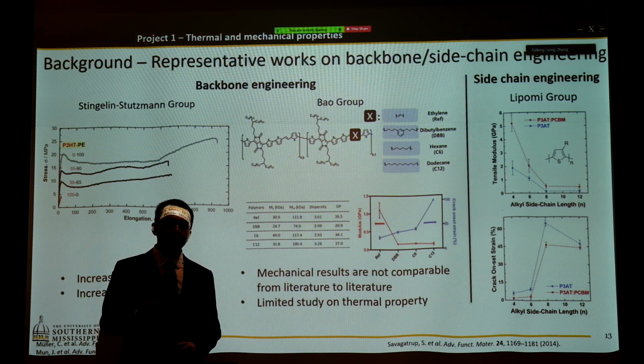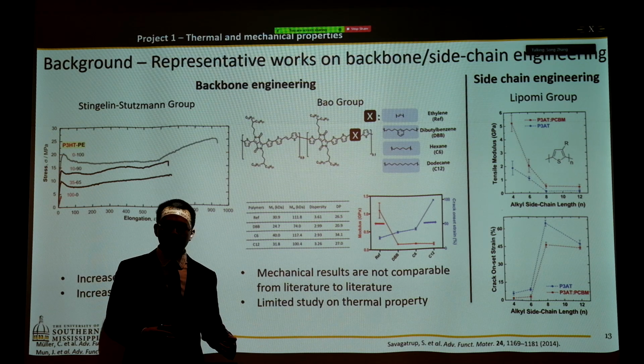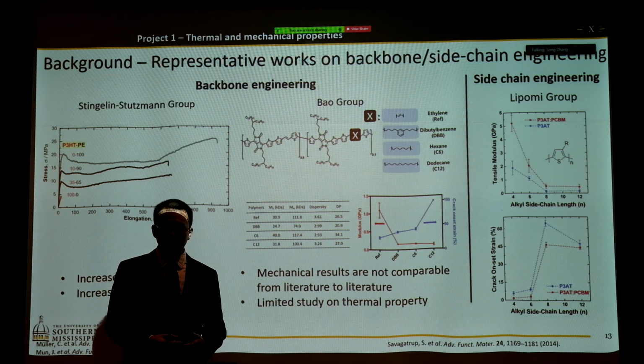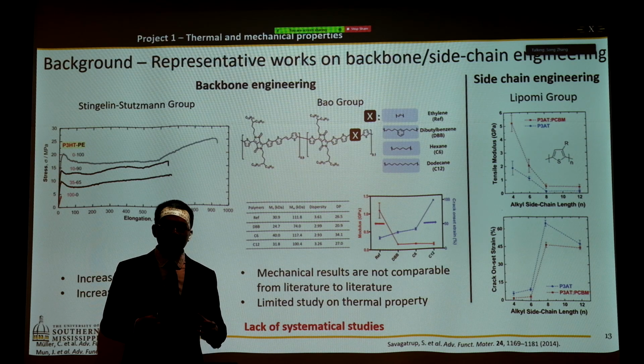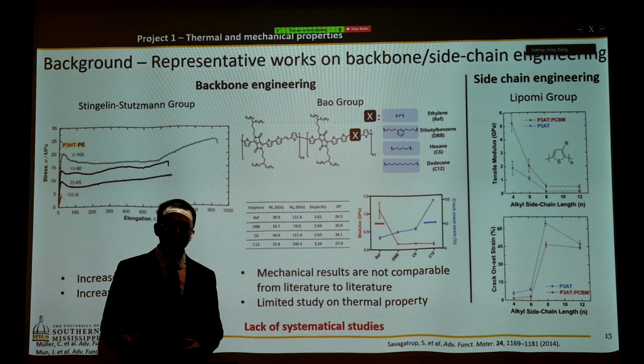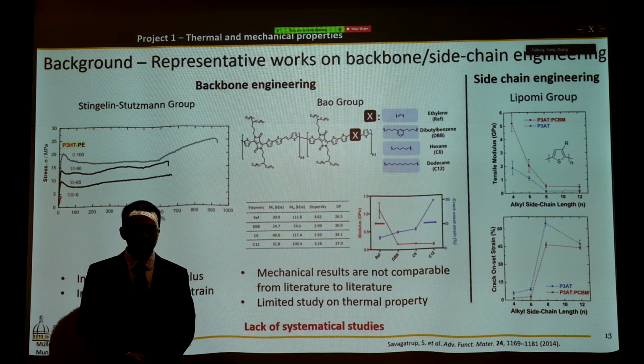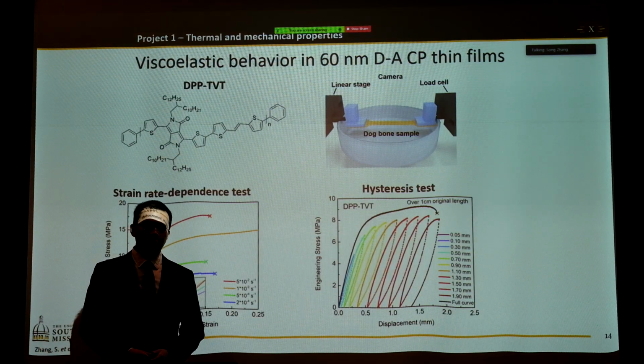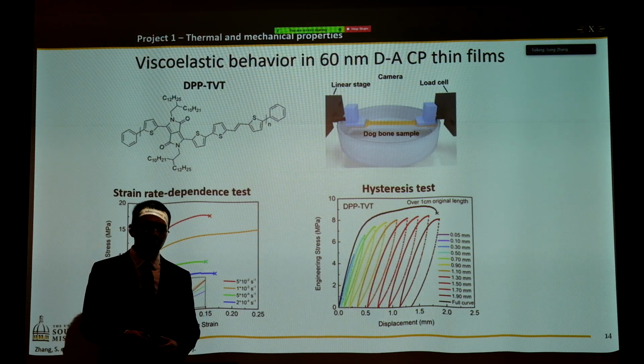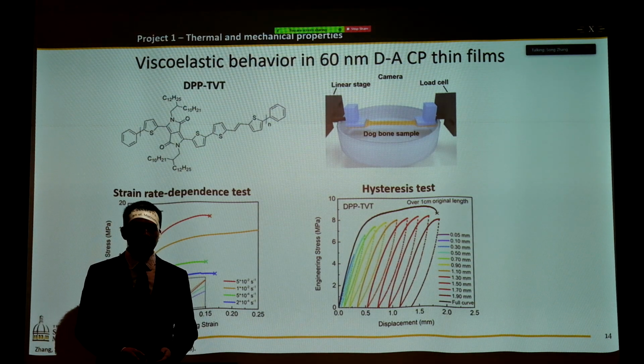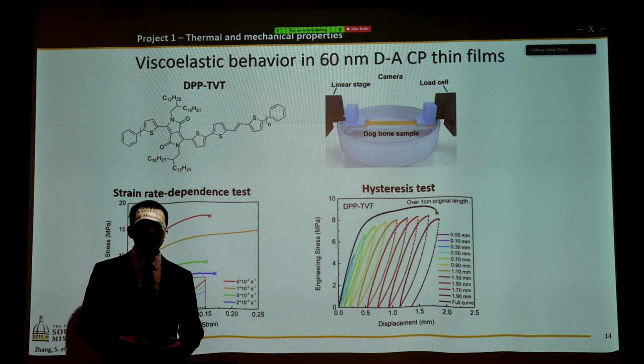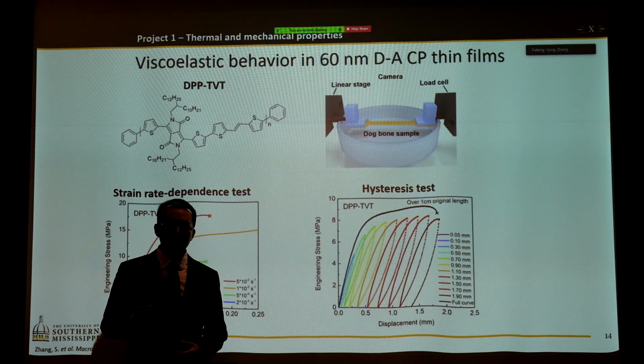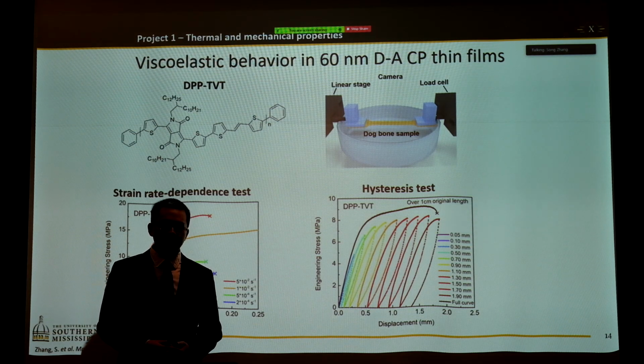And also, there is a limited understanding of the thermal behavior for the conjugated polymer backbones. And with that, we want to fill in that knowledge gap and provide a more systematic study on the quantification of backbone effect as well as sidechain effect. So our first study starts with the understanding of the donor-acceptor polymer called DPP-TVT. And here is the structure. Previous literature has informed us donor-acceptor polymers have a super rigid polymer backbone, and that makes them very brittle. That's almost everywhere in the literature.